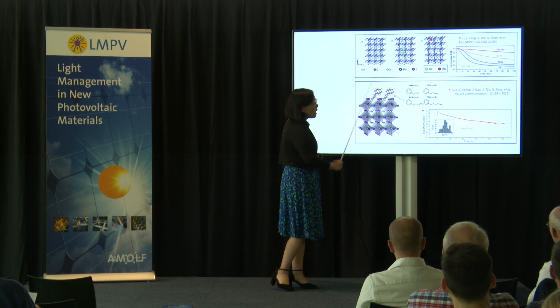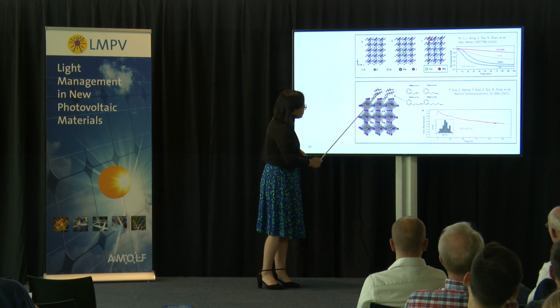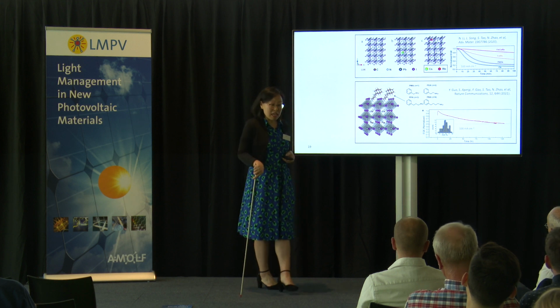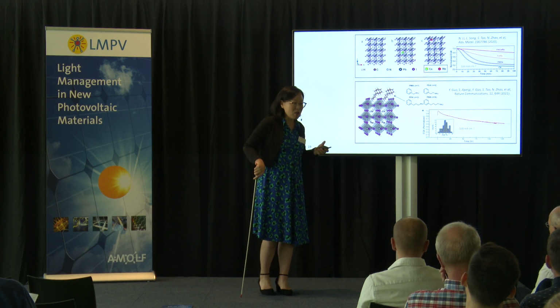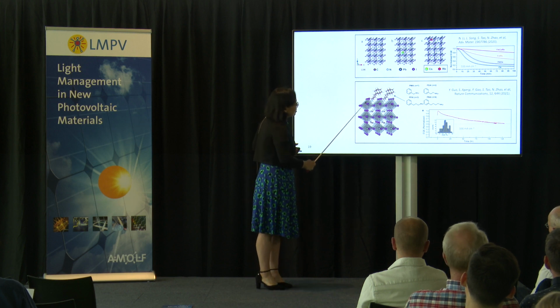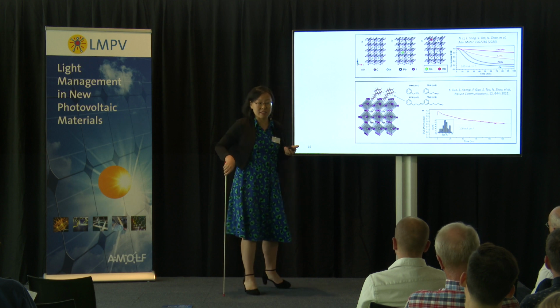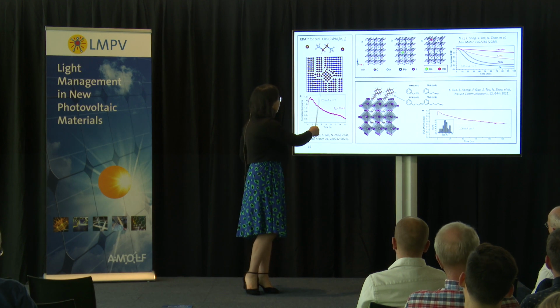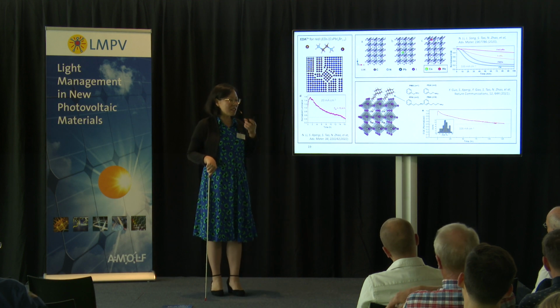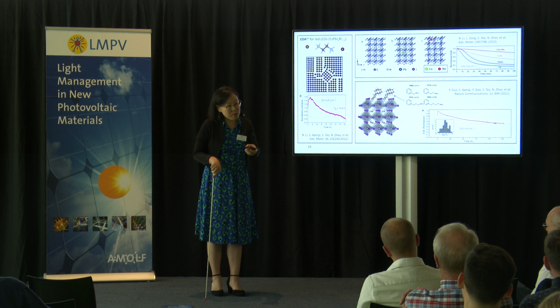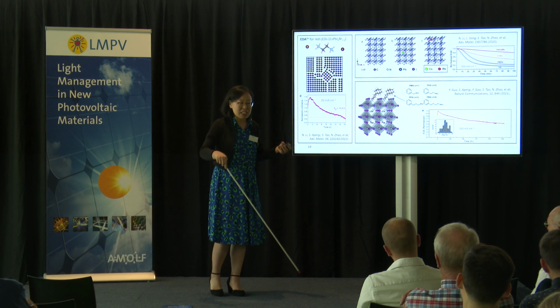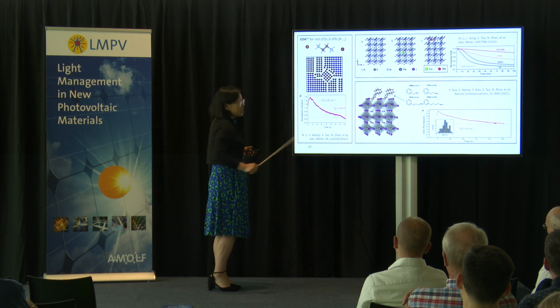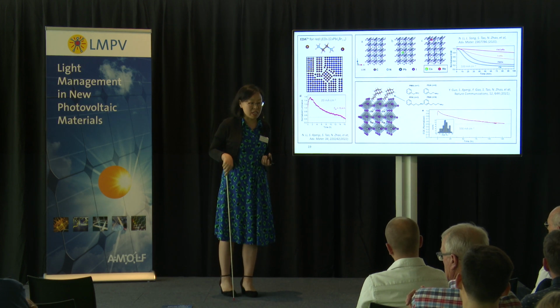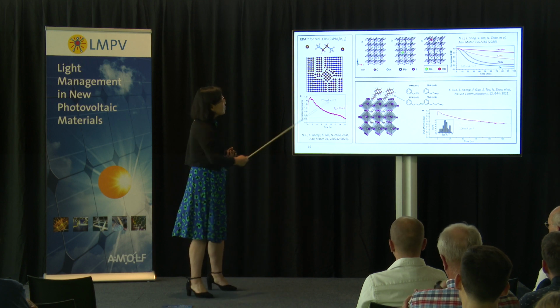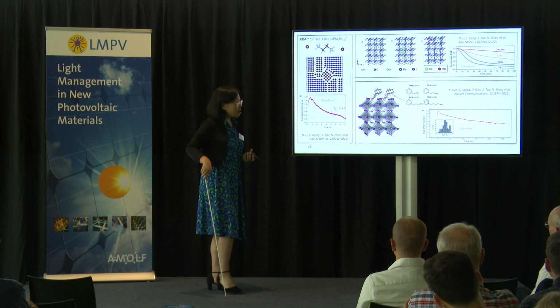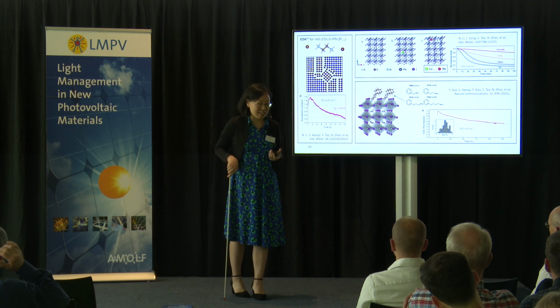We can do this using a large molecule as well. This molecule acts a bit like the cesium, as I just mentioned. But now it's longer, and its ability to hinder the ion movement is even more pronounced. Again, another molecule with 2 heads, and this molecule is interesting: the thermodynamics just allow it to be in the film but not in the bulk. It lands on the grain boundary. And this relaxes the strain between different grains. The relaxation allows a bit stronger passivation of the halide and the atoms around. As a result, all the LED devices obtain a slightly increased operation stability.